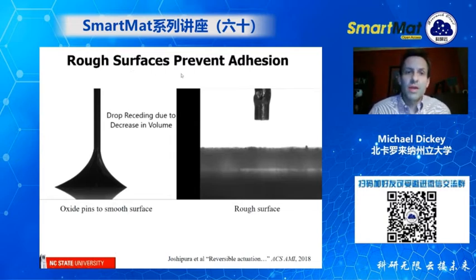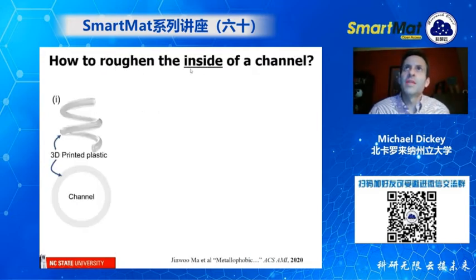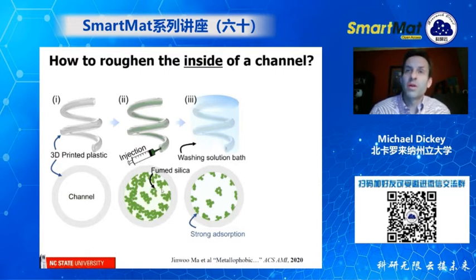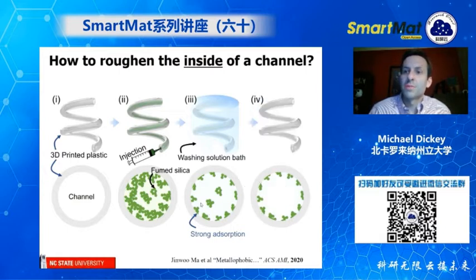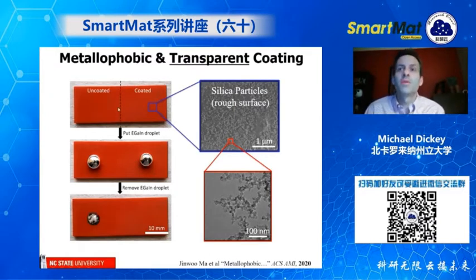So now the challenge is, if that's the case, how do you make the inside of a channel rough? So here's a piece of plastic that's been printed, and we want to make the inside of this channel rough. So the way that we did this was by injecting some silica particles, these little grain particles, along with a little bit of solvent, and it makes the walls sticky. The particles stick to the wall, and we then rinse these channels out, and you're left with this rough surface. The nice thing about this coating is that this is a piece of plastic that's been 3D printed, and on this side there's no coating, and on this side it's coated. You can't tell any difference. In fact, this coating is transparent because it's so thin.